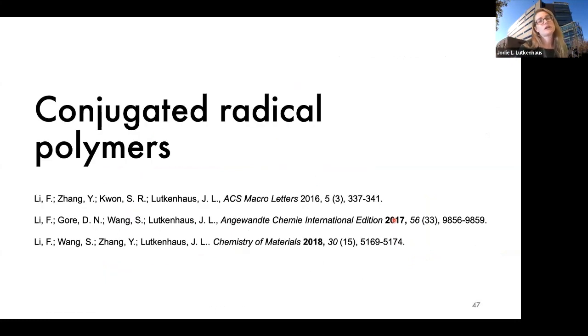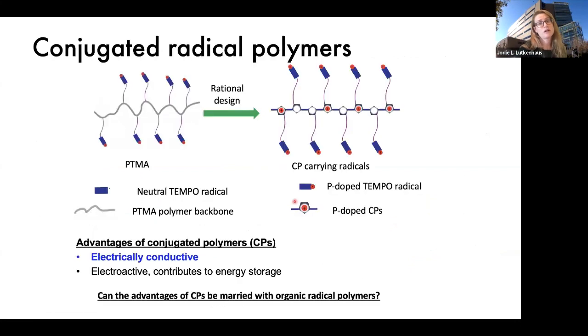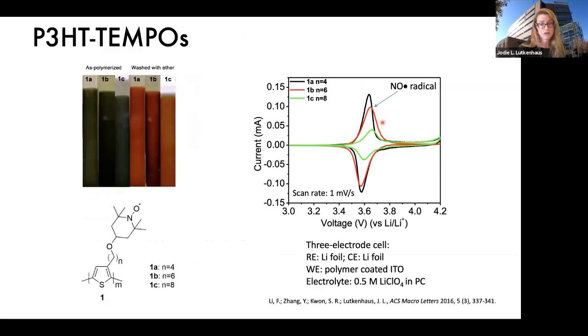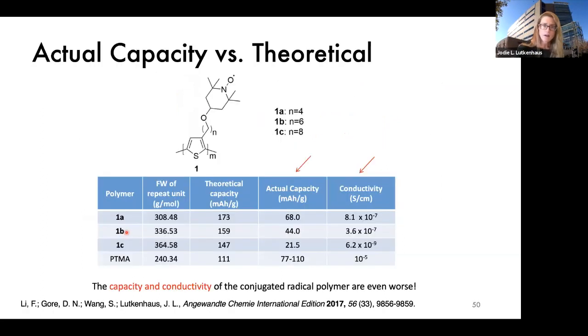Radical polymers really are not very conductive. So there's been a lot of work on adding a conjugated backbone to possibly enhance the conductivity or even the electrochemical activity. But to date, most of that work has resulted in terrible conductivities and electrochemical activity. And we wanted to understand why. So we have a series of papers where we worked with P3HT that's been linked up to a TEMPO group. And we've examined and shown that indeed the actual capacity of these polymers and their conductivity for a series of carbon spacers is really terrible. And we have now shown why.